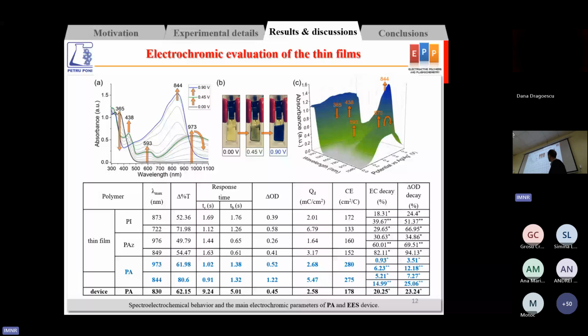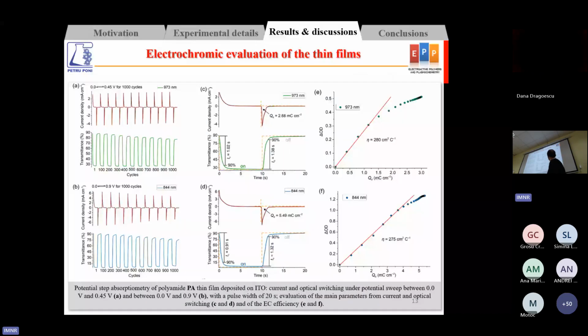Then, as the potential increased higher, new absorption bands started to emerge also in the near region of light, also associated with the second oxidation process and changing the color to blue. Then we tested the stability and the main electrochromic aspects, including the efficiency and the time response. The polymers show very fast response towards bleaching and coloring, and good stability for both oxidation processes up to 1000 cycles.